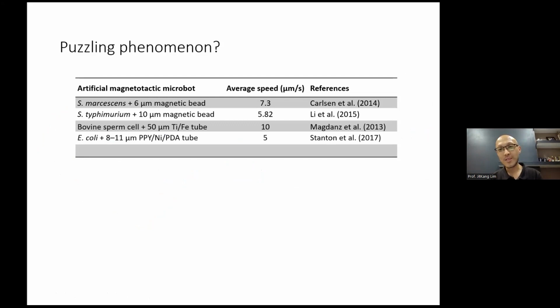However, there's one caveat. When we think about attaching magnetic particles onto the swimming cell, and we search the literature, there are a lot of ideas, and people are using all kinds of different cells. For example, here there are so many different kinds of cells combined with magnetic beads, which are not nanoparticles anymore, they're micron-sized particles of all sizes. Eventually they all reported they managed to control the motion of particles and alter the average moving speed of this construct, which is the microbot construct.